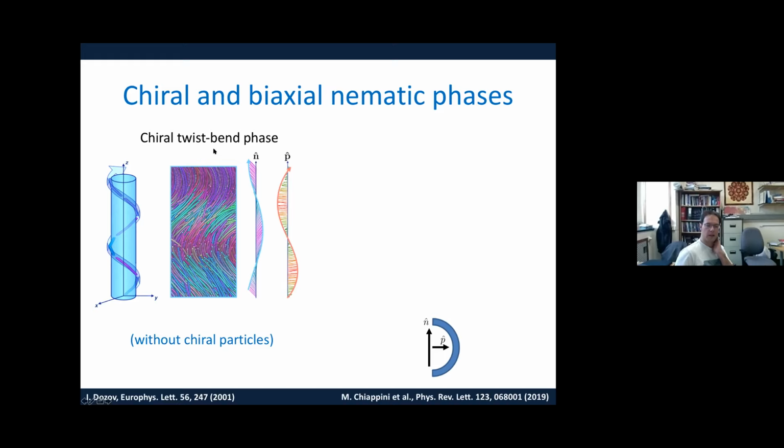It's a little bit difficult to show, but what it really does is, if you think about this cylinder as sort of a hypothetical cylinder, these particles wrap themselves around it, which means that the nematic director is always along the vertical axis of this cylinder. So you really have a nematic phase. And because it can sort of go up as on a circular staircase, left-handed or right-handed, you really have a chiral phase. And that's a twist-bend nematic phase. It's not a biaxial phase, but it is a chiral phase made of these bananas.